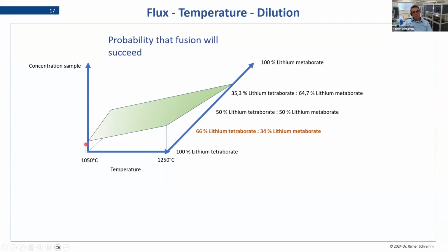That means there will be a region where your sample is still dissolving, and there will be a region where you will not be able to dissolve the sample anymore. So this will define your dilution, your concentration. If you increase the temperature, you are able to dissolve more sample into it. This is why it goes up here. And then lithium tetraborate is the flux, which is able to dissolve the most of the material.